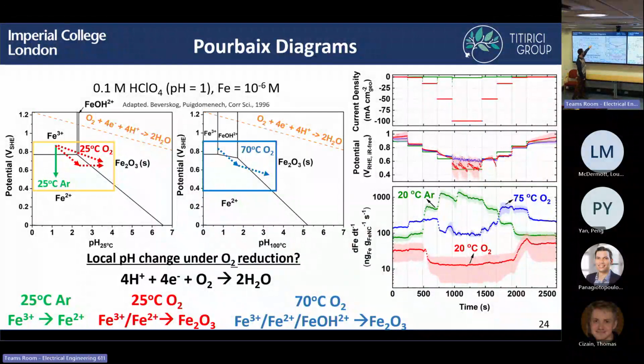So as you step down in potential, what seems to be happening is when we have this small current density, so going from 0.9 to around 0.75, we have this increase in iron concentration at these low current densities, so up to around 15 milliamp per centimeter squared. So we seem to have an increase in iron concentration because we're stepping from iron 3+ to potentially an iron 2+ region. And then as we go to high current density, we end up forming this iron oxide, which is why we have a decrease. And the reason why the concentration seems to be higher in general, we think, is just because of a faster mass transport of iron and also protons within the catalyst layer once you increase the temperature. So hopefully this makes sense so far.